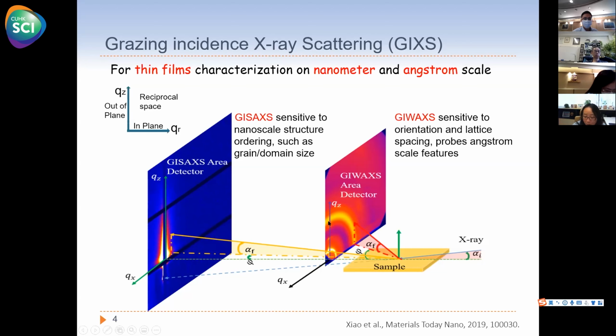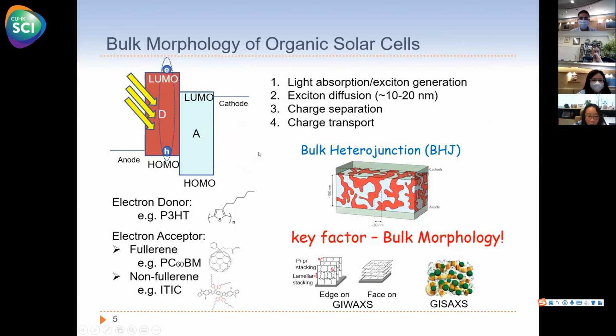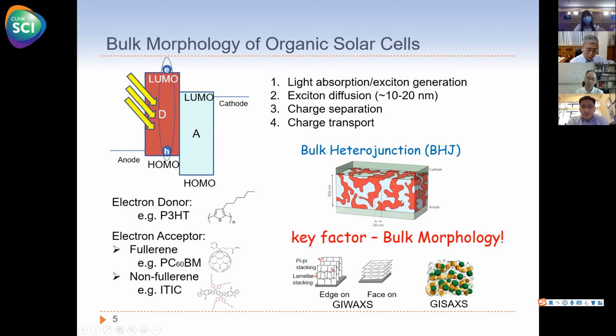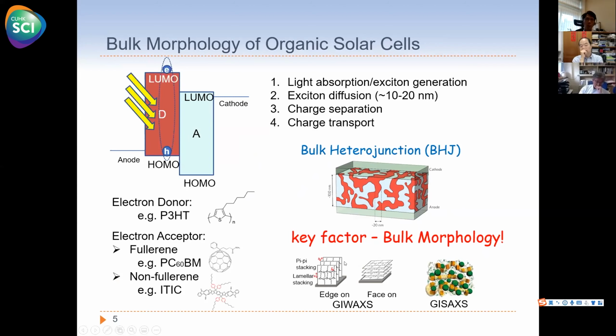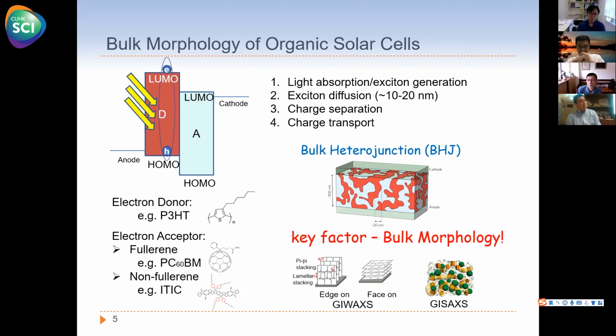In the following, I'm going to give you several examples of how we use GIWAXS and GISAXS to investigate organic and perovskite solar cell structures. For organic solar cells, people are using organic semiconducting materials, P-type and N-type materials. We call these donor and acceptor. We mix them together to form a bulk heterojunction so that we can have sufficient interfaces for the photogenerated exciton to be dissociated into electron and hole. This bulk morphology of the active layer, in other words, how the organic molecules pack inside the active layer and how the donor and acceptor materials nanophase separate, is key to the device performance.